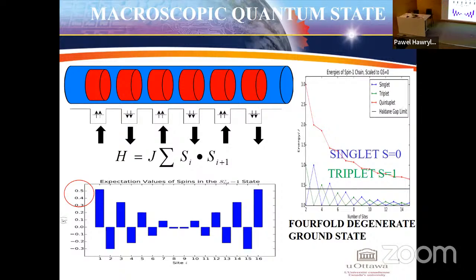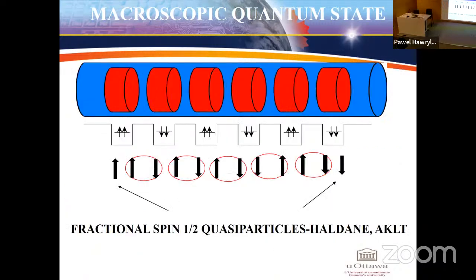2 effective spins 1/2 is 4 states if we combine them, and that exactly reproduces the degeneracy of this quantum system. And now we have these fractional spin quasi-particles, and we can forget about everything else and just focus on these Haldane quasi-particles at the edges, and they know about each other. This is a quantum system that extends over macroscopic distance. So I have a 1 meter long wire, and this Haldane quasi-particle knows about this Haldane quasi-particle.